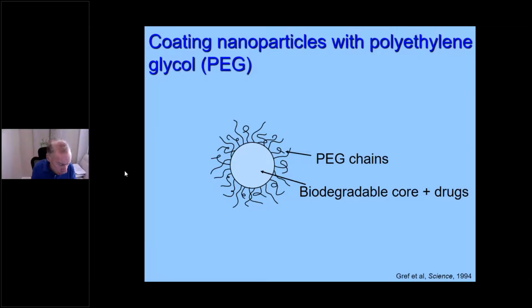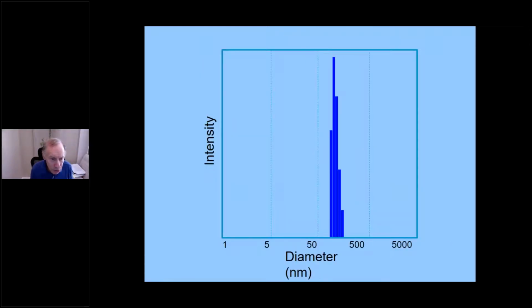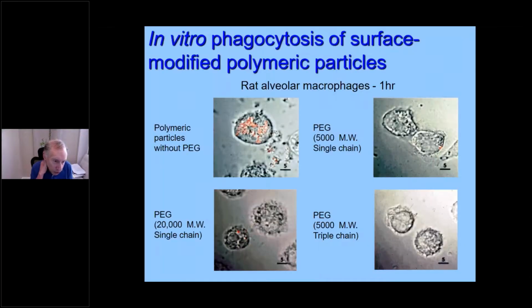But anyway, we wanted to use this disguise with polyethylene glycol because it would look like there'd be a lot of water. It would attract a lot of water, and if you see water, the macrophages, which normally clear these particles, will probably clear them much more slowly. That was the idea. We published this in Science. The next slide just shows that they are in fact nanoparticles. This uses quasi-elastic light scattering, and the next slide really just shows how effectively they work. We put an orange dye in them